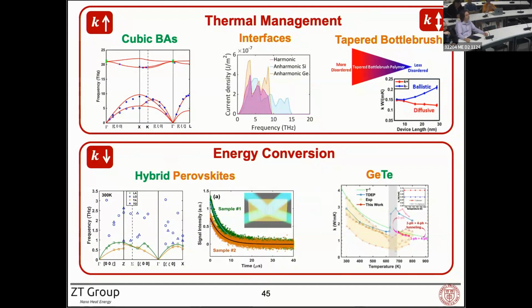So may I just ask a clarification? Why, when you include infinite terms for the anharmonicity, does it not depend on temperature anymore? Because it's the exact Taylor expansion around the harmonic point. Now, if you take the real Born-Oppenheimer energy landscape, you expand up to infinite order in the Taylor expansion, you get the exact potential, which is always the same and doesn't depend anymore on the temperature.